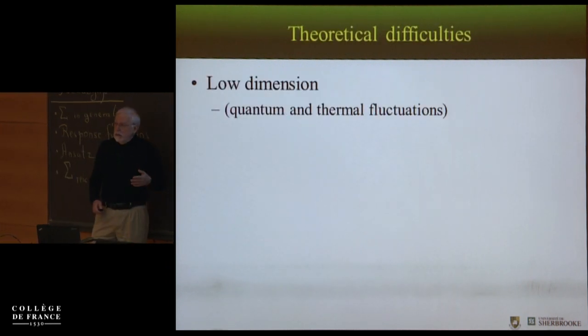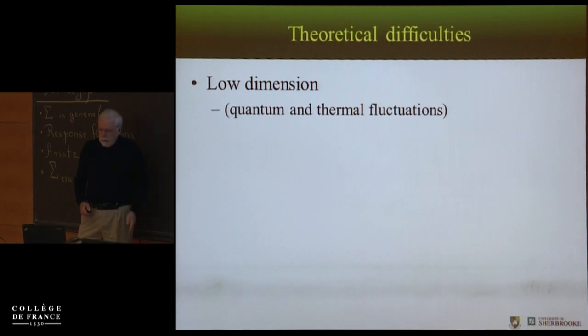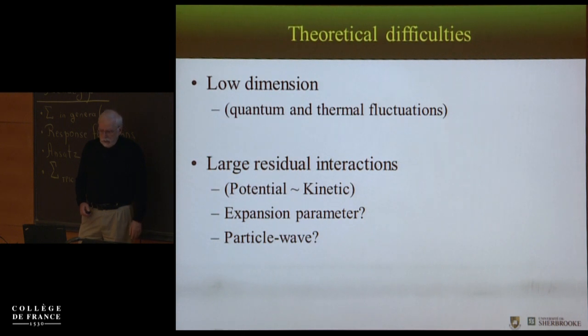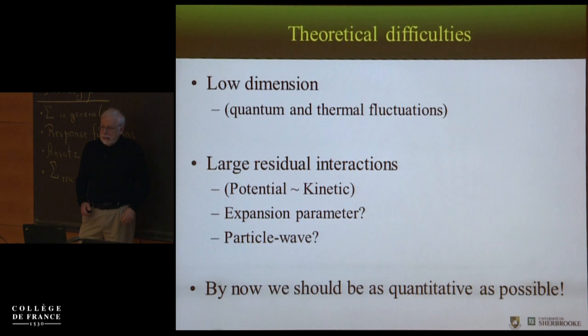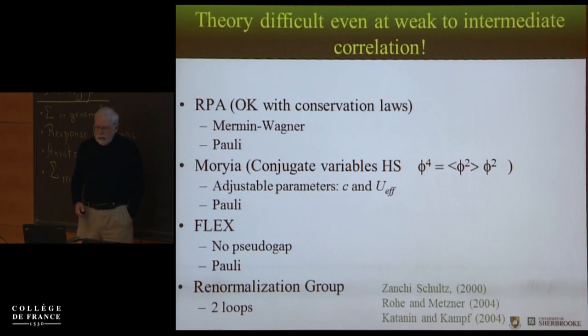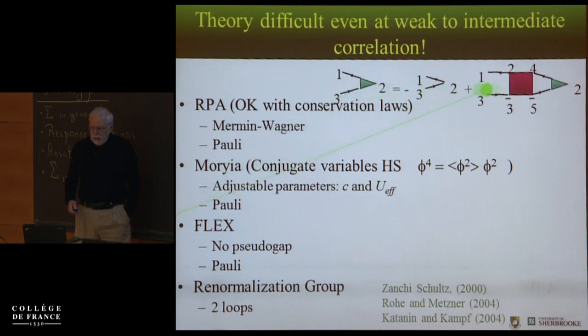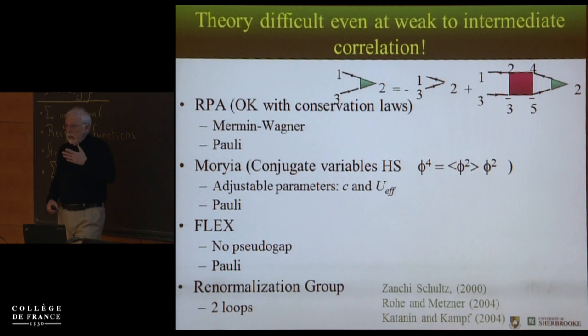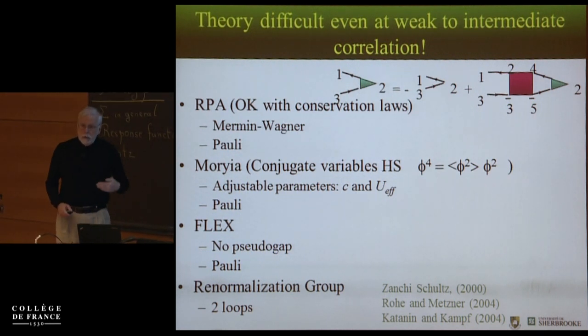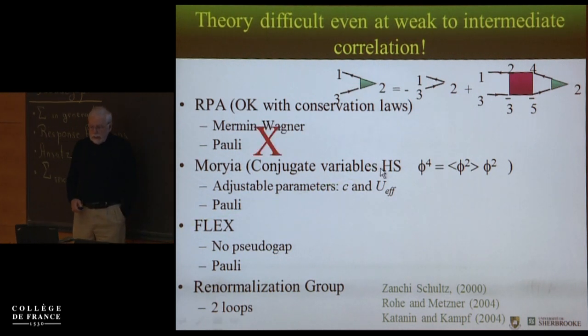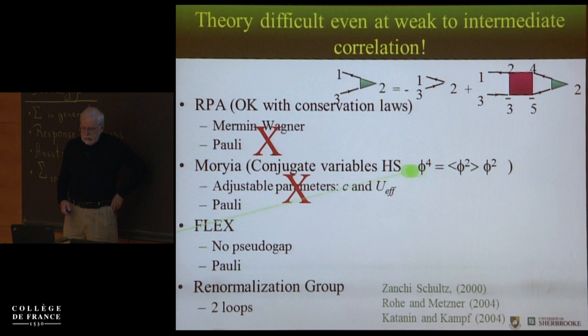Now we know that the theoretical difficulties we're facing are low dimensions, where quantum and thermal fluctuations are important, and large residual interactions, and that by now we would like to be as quantitative as possible. So even in the weak correlation regime, I've shown this before, if you do just an RPA calculation, you're okay with conservation laws, but you don't satisfy the Mermin-Wagner theorem that tells you that antiferromagnetism should show up only at zero temperature in two dimensions because of thermal fluctuations. And also you don't satisfy the Pauli principle. In the Moriya approach, you need to do this type of factorization in a Hubbard-Stratonovich transformation, and you have two adjustable parameters, the coupling constant here and U effective. So you lose the link with the Hubbard model, and also you don't satisfy the Pauli principle.